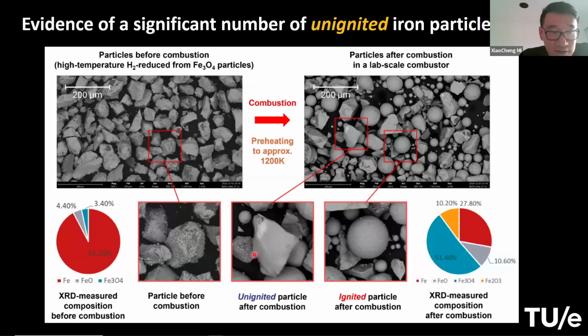And in this one, you see the surface become smooth, like all the pores are gone, right? Yeah. So this is one of the pieces of evidence that makes us believe this oxide layer is built up and covers it. And actually, there is better evidence I didn't include in the slides. We do this cross-section view, and then we do EDX, energy-dispersive X-ray, and then we can see the elements. So indeed, those irregular particles after combustion have a thin oxide layer around them.